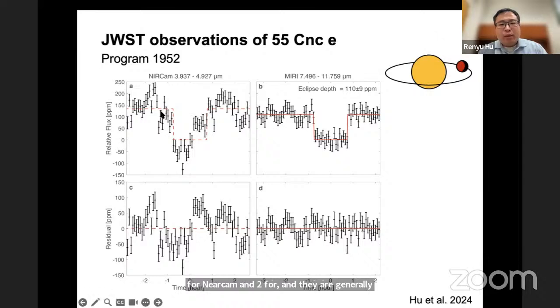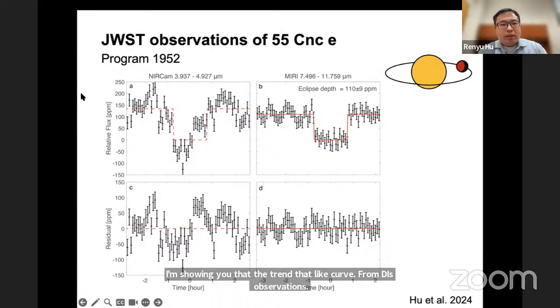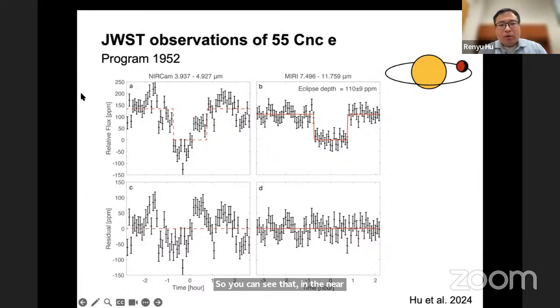Here, I'm showing you the detrended light curve from these observations. So you can see that in the NIRCam light curve, it shows quite a bit of correlated noise on the time scale of about an hour, which is the same time as the eclipse, and with a magnitude of about 50 ppm. And this prevents us from deriving a measurement of the eclipse depths in the NIRCam band. Instead, this correlated noise does not exist in the MIRI light curve, and from which we can derive a precise measurement of the eclipse depths.